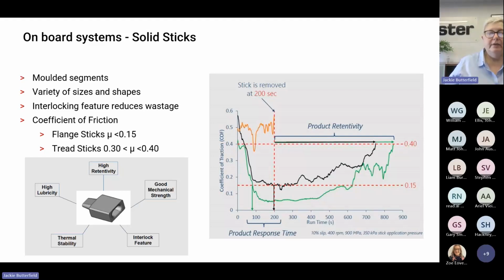And the test is dictated in the European standard, EN15427, which dictates that a 200-second stick application, to pass the test, it has to go below 0.15. And then the retentivity is the time between the removal of the stick and when the coefficient of friction reaches 0.4. So you can see that this compares three different sticks. Some are good, some are not so good, some are not very good at all.